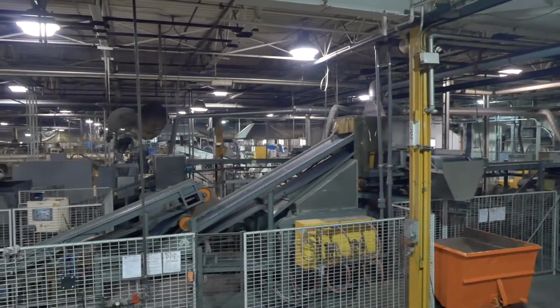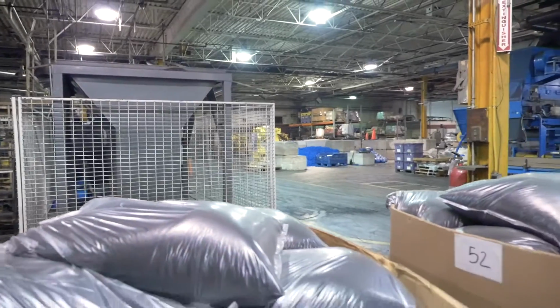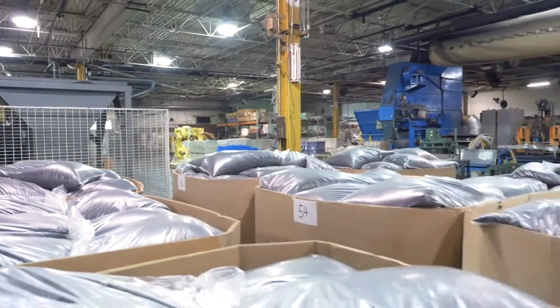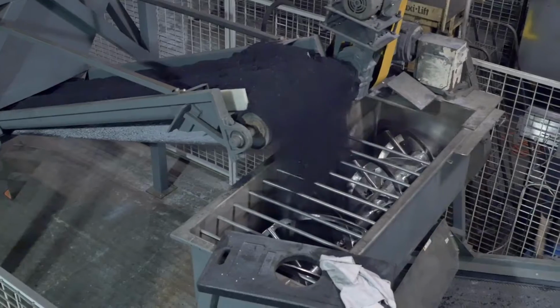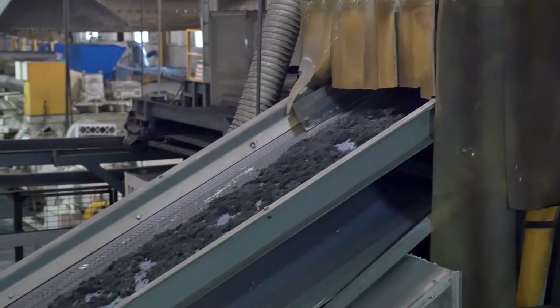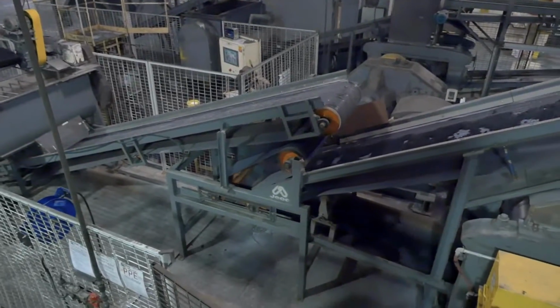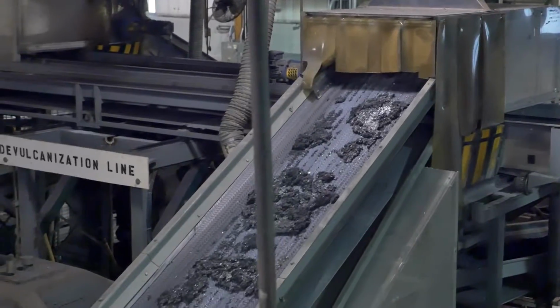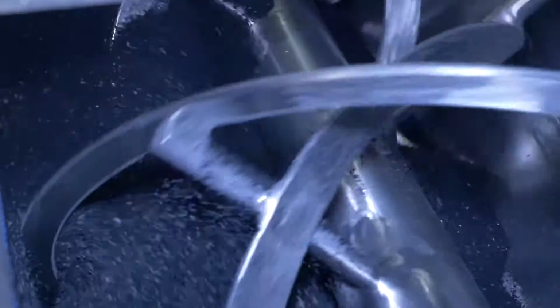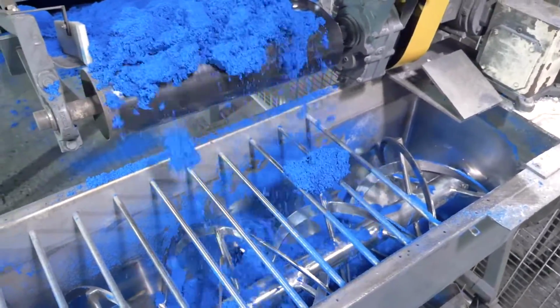NRT has a patented rubber de-vulcanization process which largely reverses this curing process and transforms the granulated rubber crumb into a chemically reactive polymer capable of reincorporation into rubber and thermoplastic elastomer compounds and products as either a partial or total virgin rubber replacement. NRT's de-vulcanization process is a dry chemical-mechanical process conducted at ambient temperature. Specified weights of rubber waste and the chemical catalysts are blended in a low-intensity mixer before being conveyed to the high-shear mechanical portion of NRT's line.